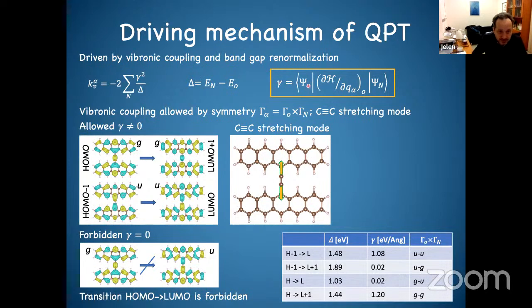Okay, so for this vibronic coupling, what I have to do is some integral of the coupling of my wave function plus some vibronic system. That means how the Hamiltonian is developing or changing with respect to all the vibrations. So I have to check all the vibrations, but here what I can advance is that the most important vibration is this mode. It's a stretching mode of this triple bond, which we see is getting weaker. Indeed there is a mode which is strongly affecting this bond length. And now, how it's changing the Hamiltonian is related to the symmetry. So if I have something which is symmetric or antisymmetric, then also my wave function has to be symmetric. It means this kind of transition from occupied to unoccupied state through this vibration is allowed.